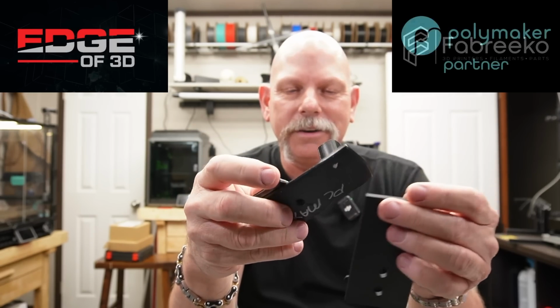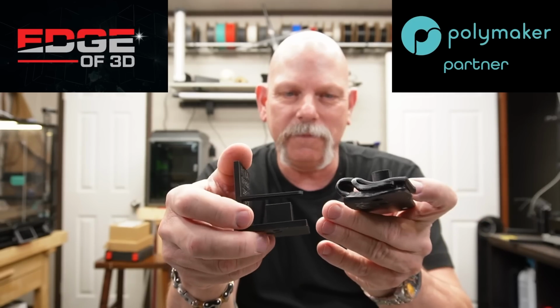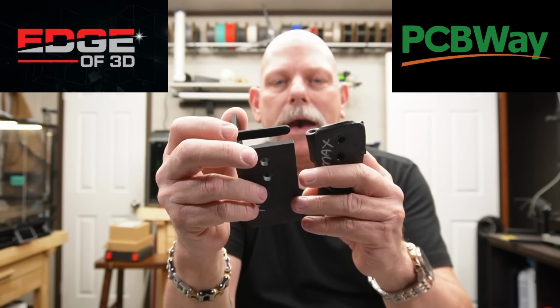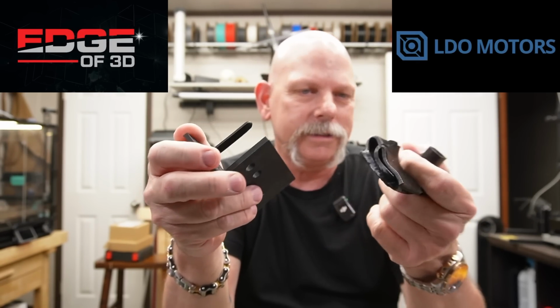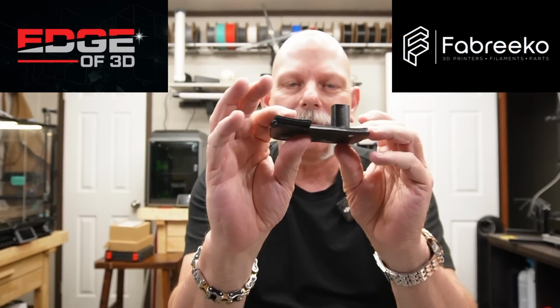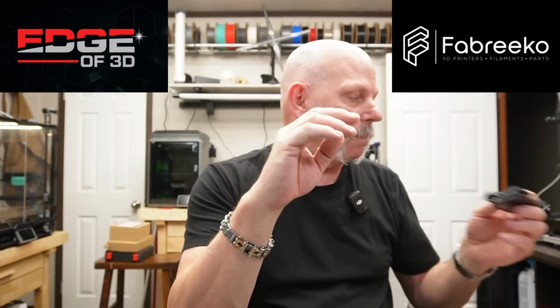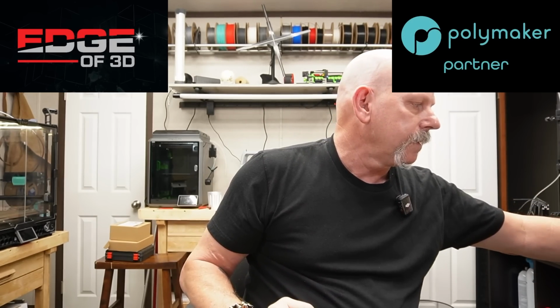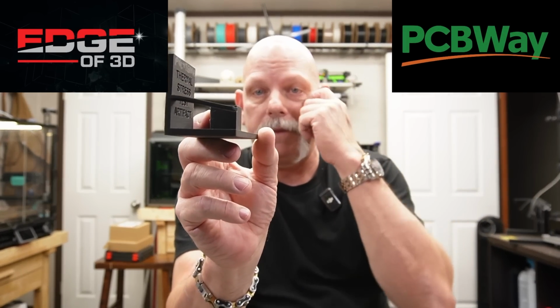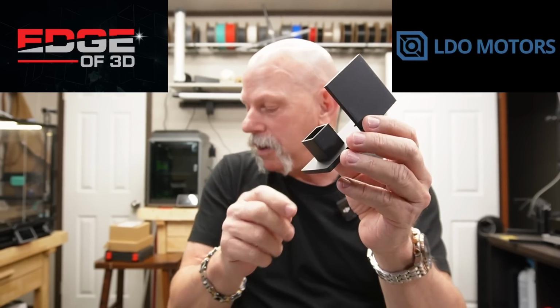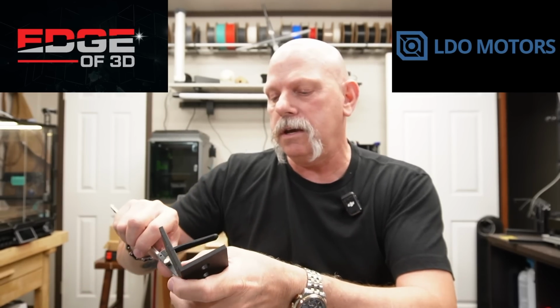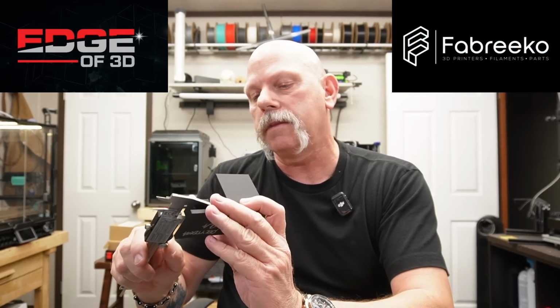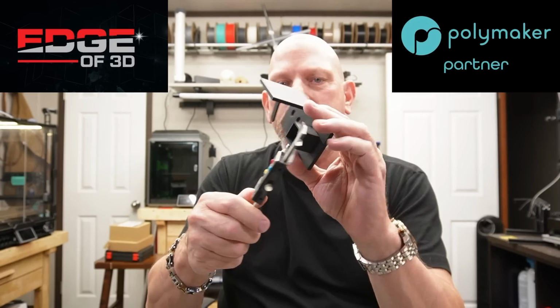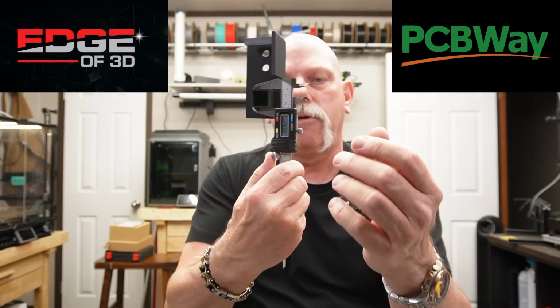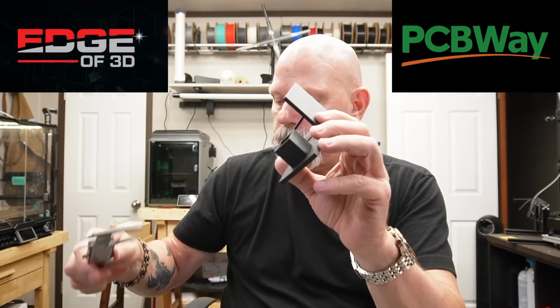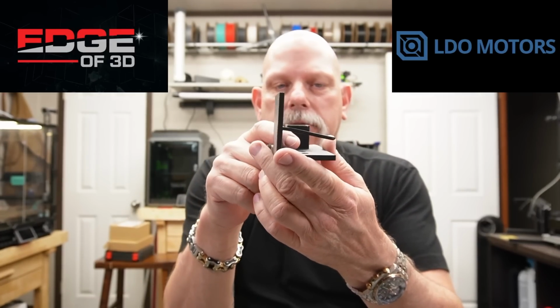It shrunk. It fell over like a bad night at a cheap bar in Tijuana. PC Max doesn't hold up to temperature. Polymaker PLA. Again, this box is supposed to be 25 by 25. Let's see how much it deformed. 24.43, 24.37. So there was some shrinkage here, but not like you'd expect from a PLA.